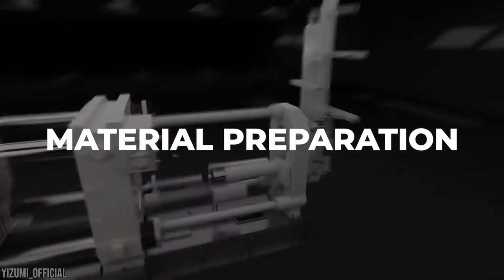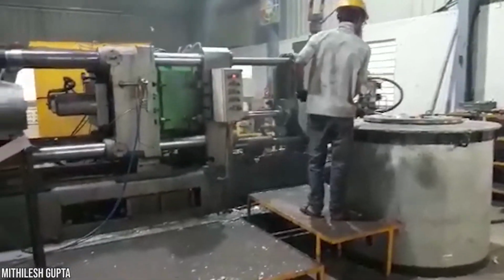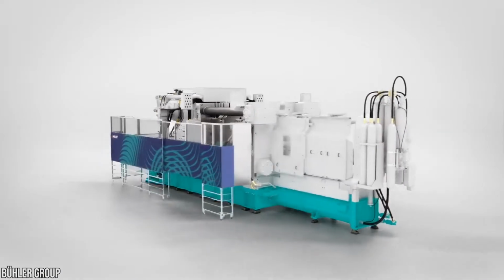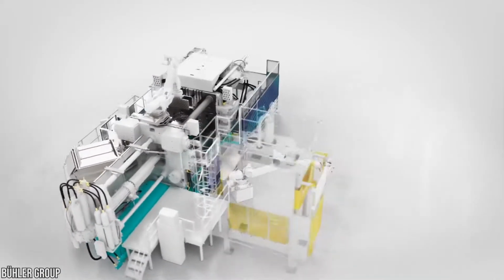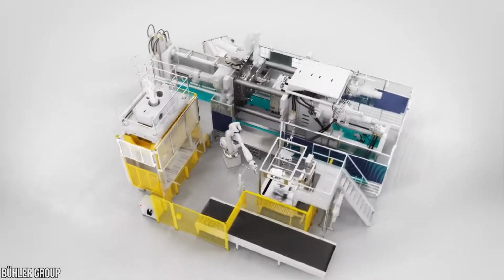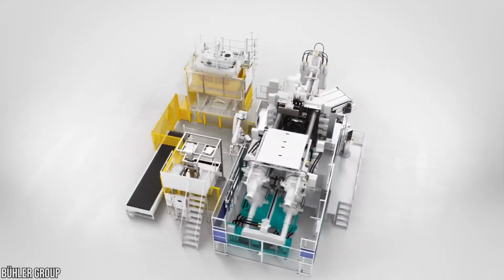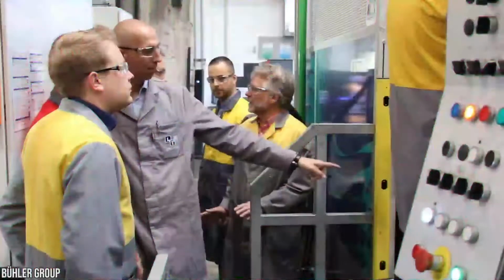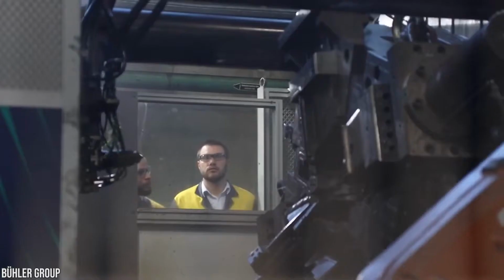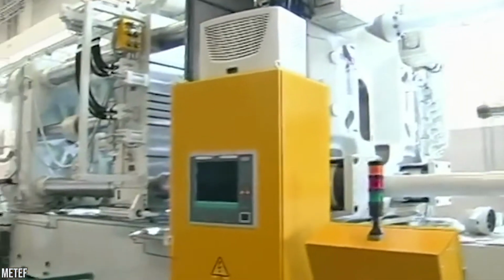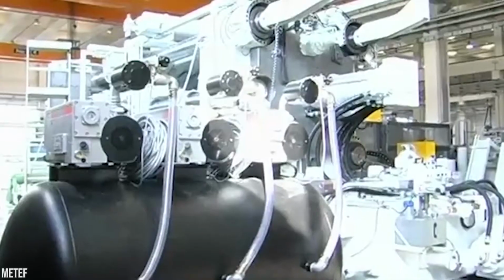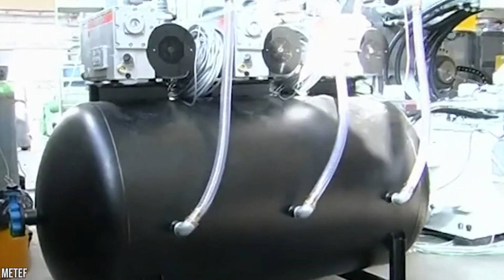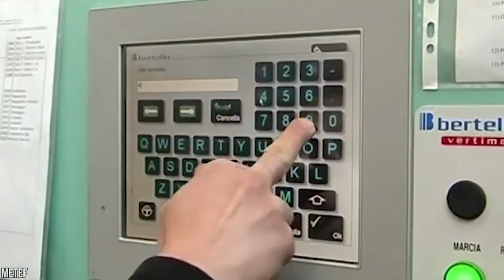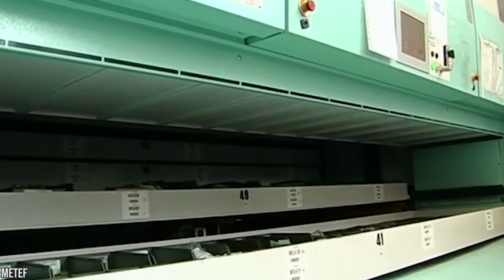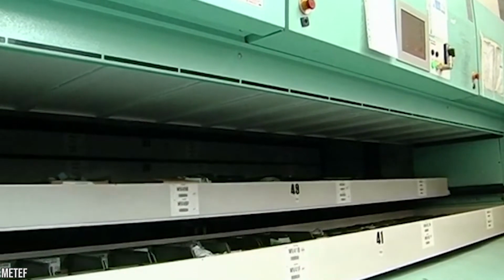Material preparation. First of all, we have to melt the aluminum ingots and cutoffs from the previous casting cycle in an oven at 850 degrees centigrade. Then remove any impurities from the surface and convey the liquid metal into another enclosed oven using heated pipes. That oven maintains a temperature of about 750 to 850 degrees centigrade. Fill empty space inside the storage oven with nitrogen gas that prevents the formation of oxides in the molten aluminum. It also helps to maintain an even temperature. Additionally, operators use argon gas, rotary degasser, and silicon carbide filters to further remove impurities.